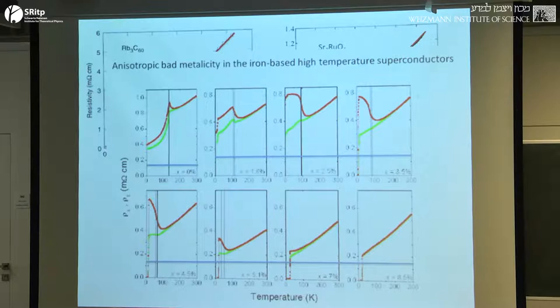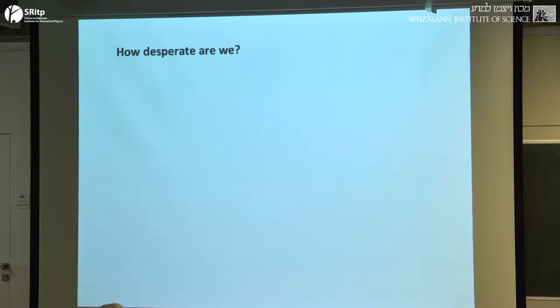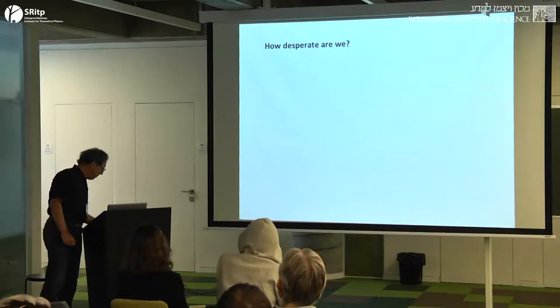Here are resistivity curves from Ian Fisher on various doping levels of one of the iron-based superconductors. It's doing all sorts of interesting things. It's resistance in two different directions, showing nice evidence of nematic fluctuations. But here, at elevated temperatures, you see this familiar, more or less T-linear temperature dependence of the resistance at values that are much bigger than the quantum of resistance. OK, so I've told you why conventional theory doesn't work. Lots of people have tried to offer theories that do work.